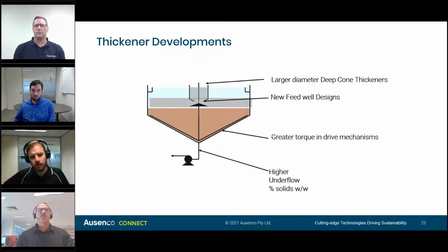So over the years, there have been a number of developments in thickeners, in particular larger diameter deep cone thickeners. We're up to around 45 meters in diameter for paste or deep cone thickeners, and that wasn't possible a number of years ago. There's also been a number of developments in the feed well, basically where we don't have to use as much flocculant, and the settling characterizations have improved somewhat.